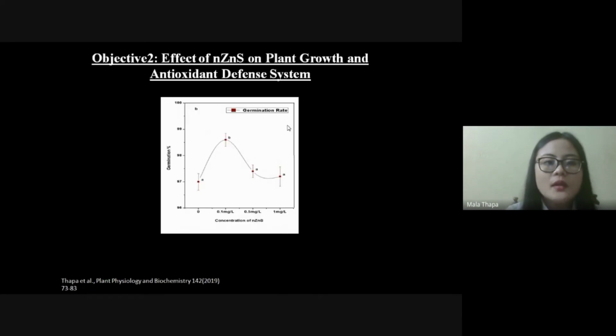Okay. Now, objective 2, effect of zinc sulfide nanoparticle on plant growth and antioxidant defense system. To understand the effect of zinc sulfide on plant growth, we have chosen mung bean plant as a model system and treated mung bean plant with a different concentration of zinc sulfide nanoparticle. Those are 0, 0.1 mg per liter, 0.5 mg per liter, and 1 mg per liter concentration, and found that the treated seeds have significant increase in germination percentage than the control.